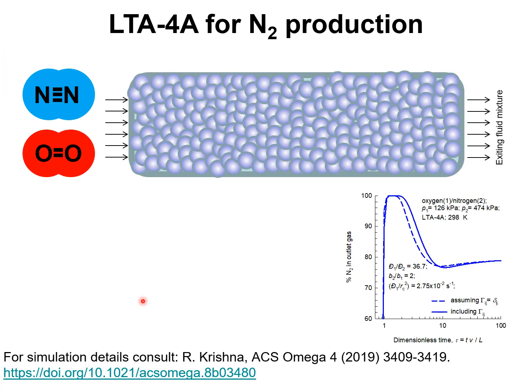To demonstrate the importance of thermodynamic coupling in kinetic separations of oxygen-nitrogen mixtures in LTA zeolite, we perform transient breakthrough simulations for 21/79 oxygen-nitrogen mixtures at a total pressure of 6 bars and temperature of 298 Kelvin. The simulation details are available in my 2019 paper.